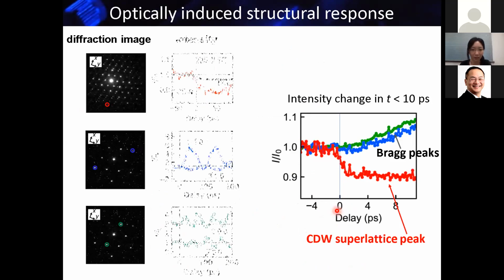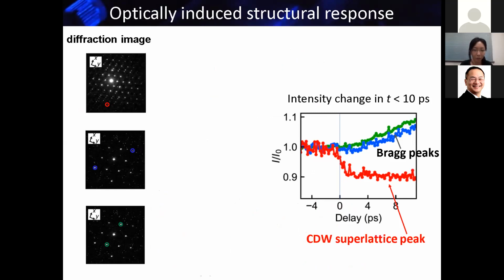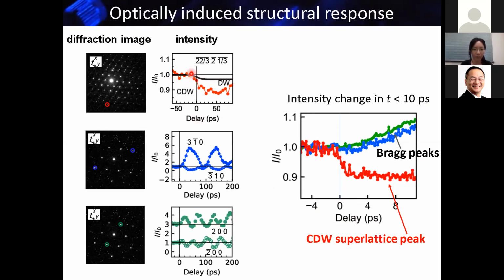Okay, so let me start. Oh, sorry. So this is a diffraction pattern obtained by the TEM. So there are many Bragg peaks around here. And when you look at the CDW superlattice peak, you can see that when we hit the sample with the light, it decreases like this. So we can see that the CDW is broken to some extent just after the optical excitation. But this Bragg peak rather changes very slowly and increases like this. So we go on to the longer time scale, and it looks like this. Okay, so the CDW first breaks like this, but the other Bragg peaks show very long time oscillations, like 100 picoseconds or 50 picoseconds. So, okay, like this.